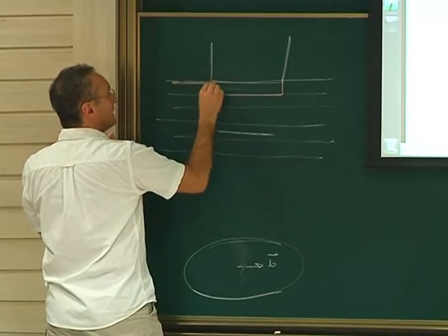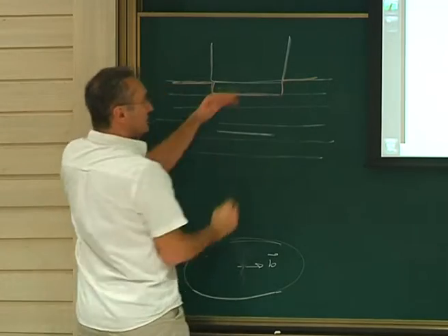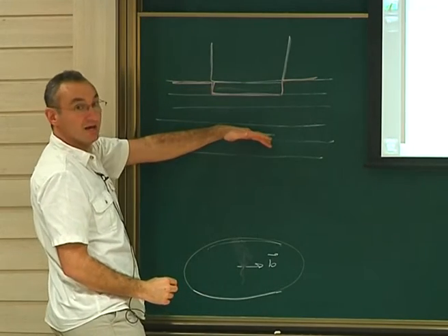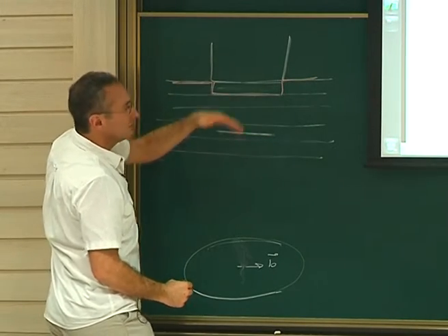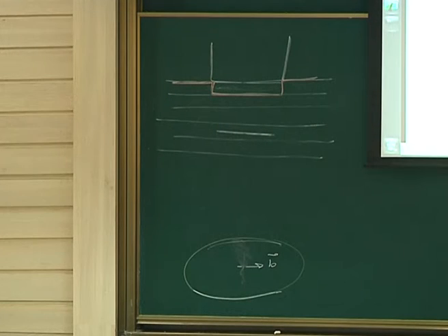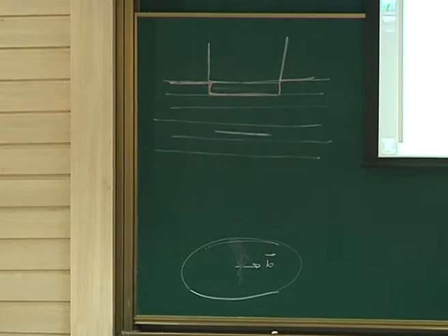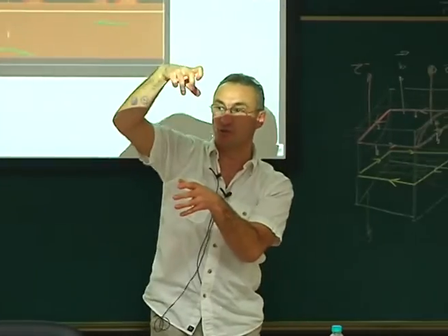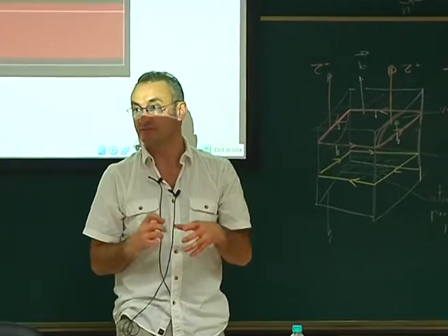There is a hole here, like that. So here there are some atoms which are missing, and here atoms are extra. Okay? And this hole is exactly equivalent to the vacancy loop. It means that some atoms are missing in the vacancy loop. So this loop creates a punch at the surface. Every time you have a prismatic loop, at the surface there is a punch or an extrusion. Extrusion if it's interstitial, punch if it's vacancy.